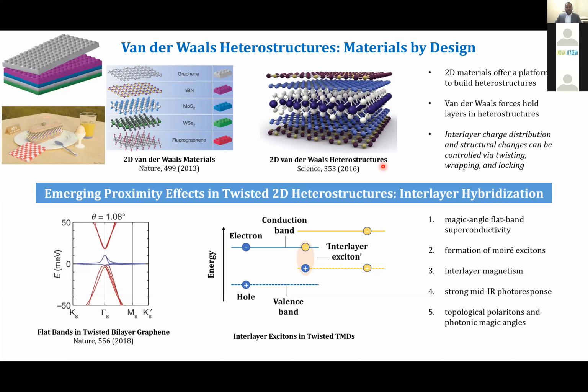So why are these Lego structures or heterostructures important? There are recent studies that if you take these structures and then you rotate them, we call it the magic angle. It's just at an angle of 1.1 degree, 1.08 degree precisely. So you will be able to see a drastic transition to a state called superconductivity. So you'll be able to see superconductivity in graphene, just if you put one graphene layer on another and rotate it at 1.1 degree, 1.08 degree. So this is one example of building Lego blocks of 2D materials, of building heterostructures.